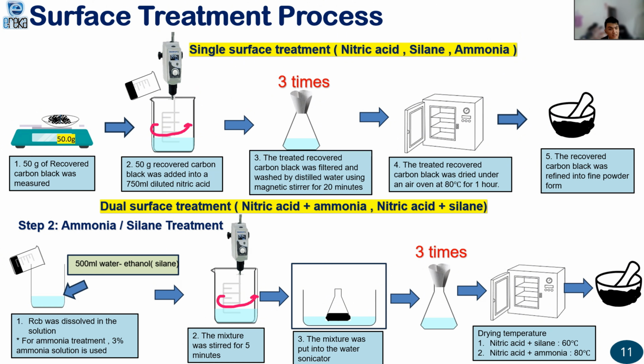Okay, so first of all, I will explain the surface treatment process, which is the single surface treatment. We will use nitric acid, silane, and ammonia. First, we will measure the mass of the recovered carbon black. After that, we will add nitric acid or the different chemicals and then undergo the stirring process using a magnetic stirrer. Then we will filter it three times, put it into the oven for the curing process, and lastly refine it into powder form.